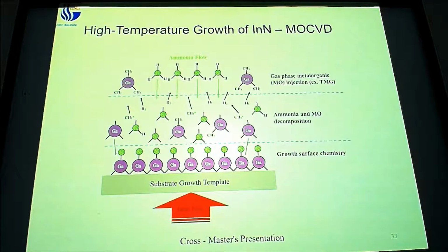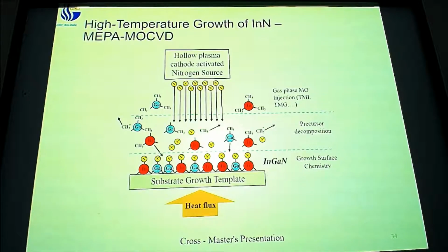So what our lab has been working on is migration-enhanced plasma-assisted MOCVD, which starts breaking down at 650 degrees Celsius. We start using nitrogen ions from plasma. What this allows us to do is work at a lower temperature, and it also changes the kinetics of the reaction at the surface, feeding more energy into the reaction, allowing the atoms to move more freely, find the right position to be in, and grow the crystal structure. And we can show this.